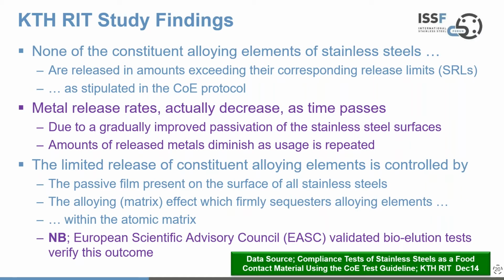So from the findings, none of the constituent alloying elements of stainless steels were released in any amounts exceeding or coming close to the corresponding release limits. And that was as stipulated in the protocol. And what was interesting is that as time progressed, particularly beyond the first 2 hours of measurement time, the metal release rates actually decreased. And that was observed to be due to a gradually improved passivation of the stainless steel surfaces. So the passive layer actually became more resistant to metal release as time progressed, and therefore the released metals actually diminished over time.